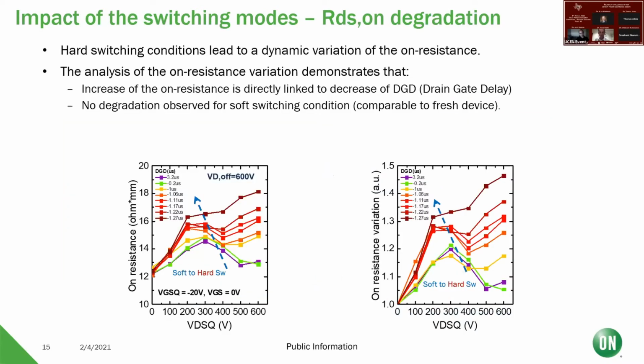Next slide shows you the RDS(on) dynamics as a function of voltage. This is, as I mentioned, intimately coupled to how you operate the device. It's a particular challenge during hard switching conditions. In fact, it doesn't really show up in soft switching configurations, but unfortunately, most of the benefits you can achieve from the speed of GaN, which is one of its key features, are in the hard switching applications. And so you have to solve that problem, or at least characterize it, so people can design with the problem in mind.